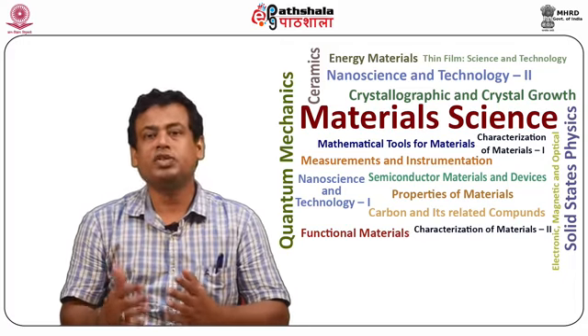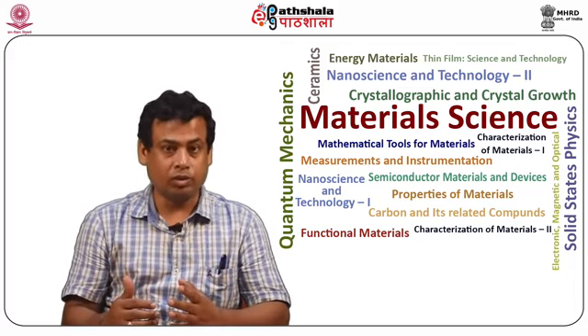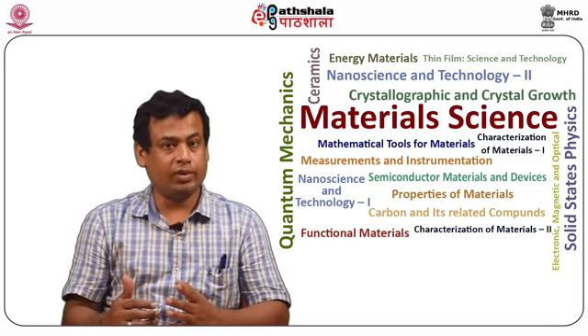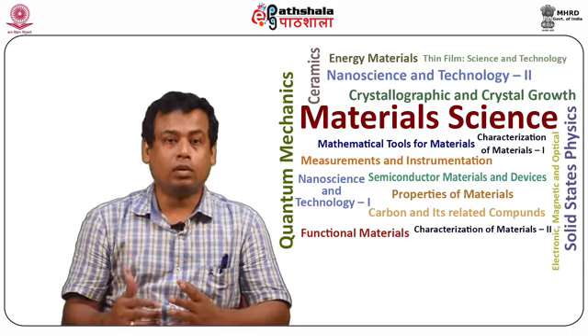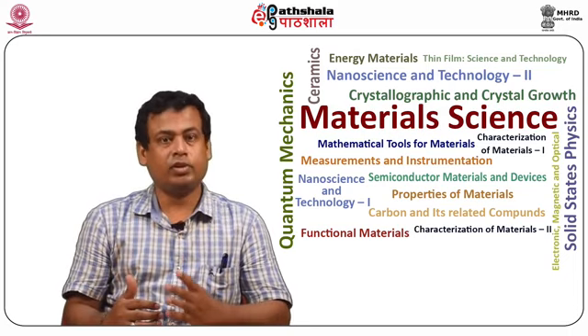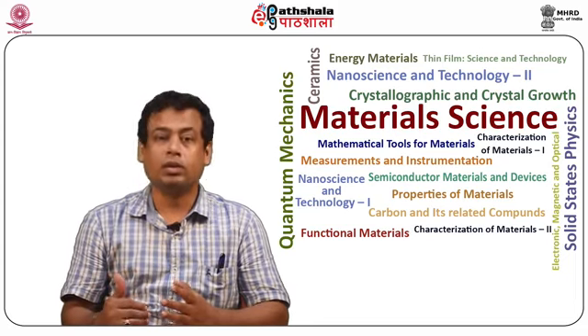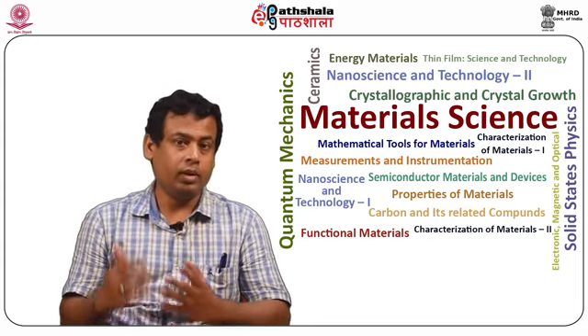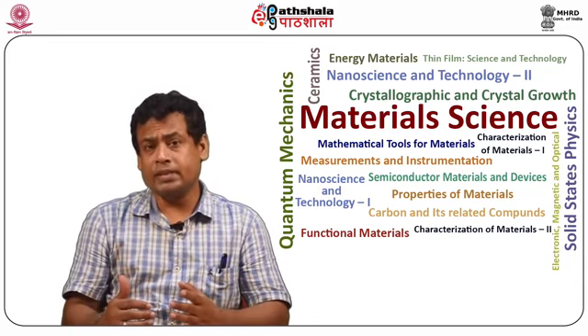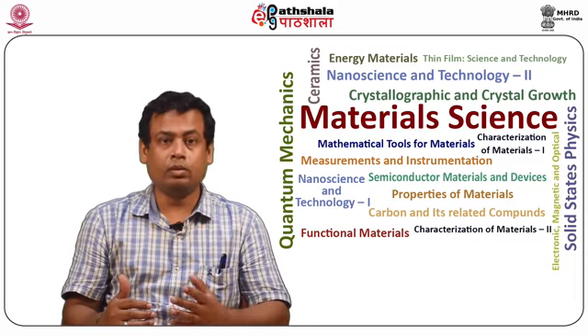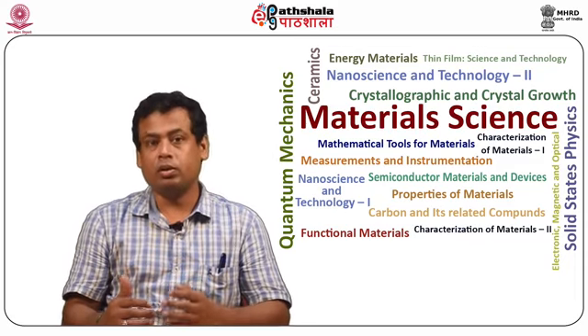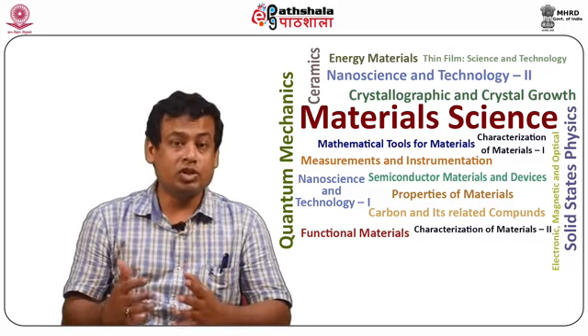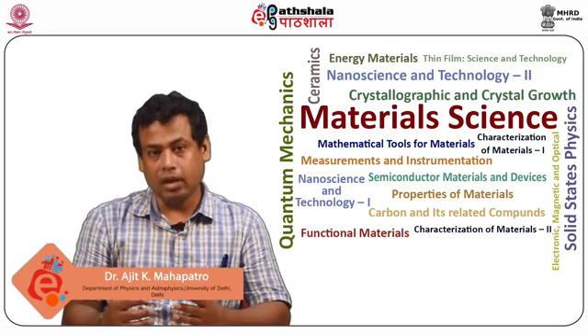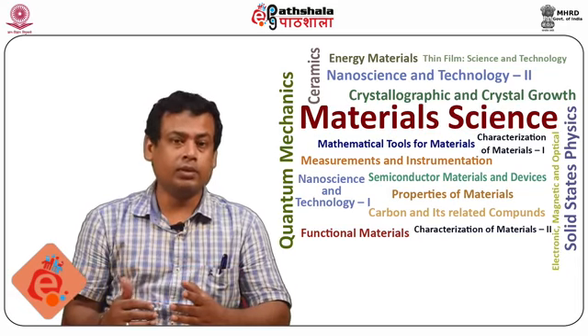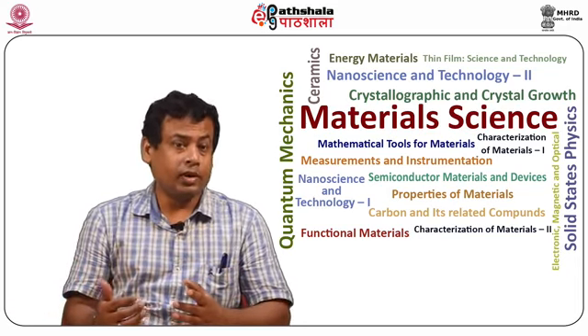To calculate the differential cross-section for an elastic collision, the principles of conservation of energy and momentum are complemented by a specific model for the force that acts during the collision between the projectile and the target masses. In most cases, this force is very well described by the Coulomb repulsion of the two nuclei, as long as the distance of closest approach is large compared with the nuclear dimensions, but smaller compared with the Bohr radius a0, which is equal to 0.53 angstrom.